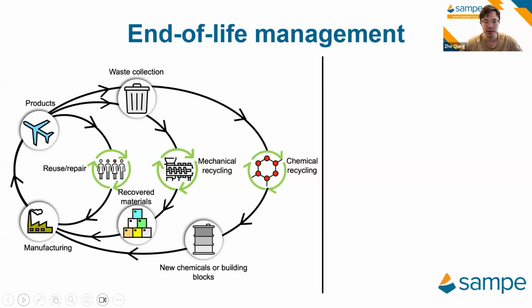So during this mechanical recycling process, we do not alter the chemical identity in general. You may have some chain scission or crosslinking happen because of the high shear, high temperature environment. But in general, the chemistry itself is not changing. So you just really try to regenerate materials. But we also recognize that the challenge of mechanical recycling is that even though you have the same material chemistry, the material properties can often be degraded, especially as a function of recycling events.